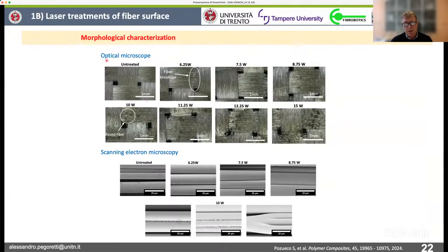In particular, by using both optical and scanning electron microscopy, you can observe the effect, which changes with the power used during the treatments. If you look at the picture, you can see that after a given power, the fabric is damaged, so it is not suggested to use a power which is too high. On the other hand, if the power applied is too low, there are basically no effects on the fibers, and therefore we have to optimize these processing parameters.